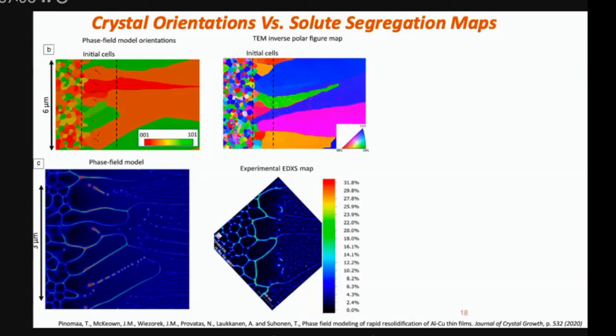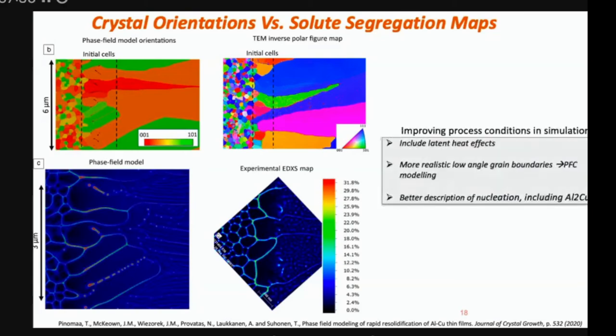The initial grain structures very quickly give rise to just a few isolated grains that have a lot of solute striations within them. In the experiments, the striations don't seem to be observed, but we see a lot of these islands of solute. It could be that there are striations, but they're just not resolved. We don't know. The point is these trapped striations and/or islands of trapped solute are all destined to become other phases. Eventually, if you cool this long enough, they're going to become intermetallics. Or they may even become voids, like literally just gaps in the material, which will then be a problem.